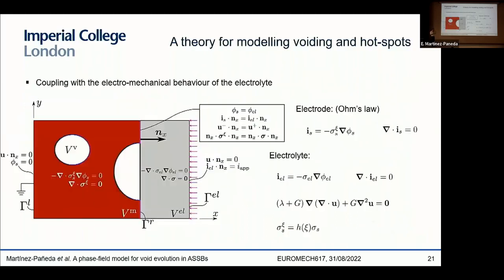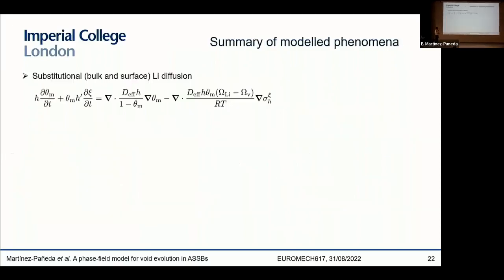And last but not least, we not only model a chemomechanical problem, we also want to solve an electrical problem. So we want to couple this description of the anode with the electrolyte. We're also solving for the electrolyte, which we assume to be an elastic solid. It's a ceramic electrolyte. And we solve Ohm's law in both the electrode and the electrolyte. And of course we ensure continuity of current and potential along the interface. And one important thing is that we interpolate the conductivity of the electrode. And this is quite important, of course, because this is what's going to create the hotspots, right? The fact that you have this abrupt change from the conductivity in the lithium metal to the void. And this abrupt change is going to lead to those current hotspots.